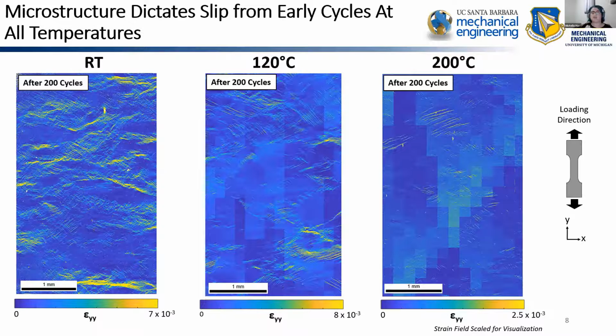Yes. So everything is loaded to a temperature adjusted yield. Is that 90% of its temperature adjusted yield strength? And so the idea is that you've dropped that fraction, does that make sense? So you've actually dropped how much you're deforming everything, because everything's acting more homogeneously. So if you think of the average response, you're at an even lower portion of.